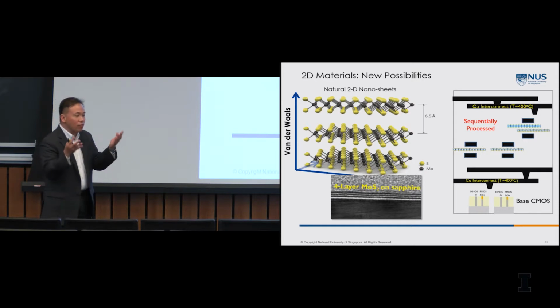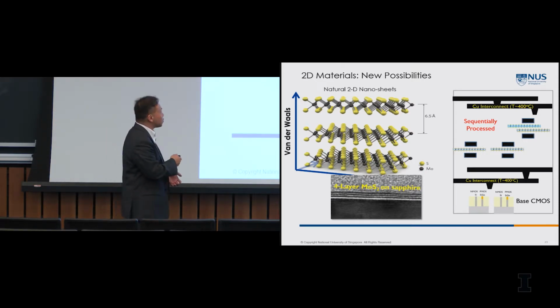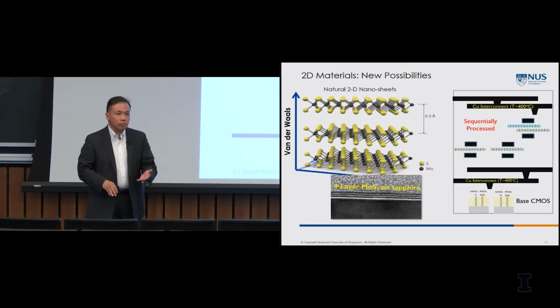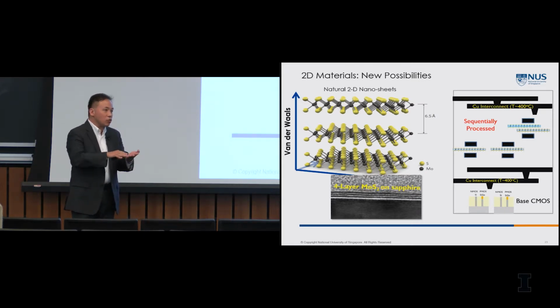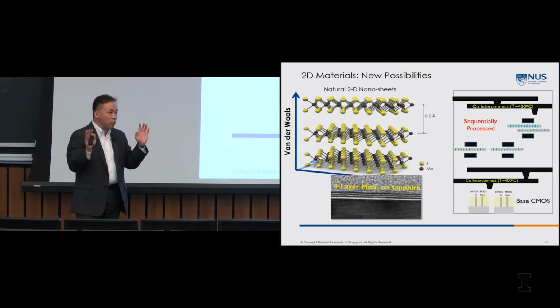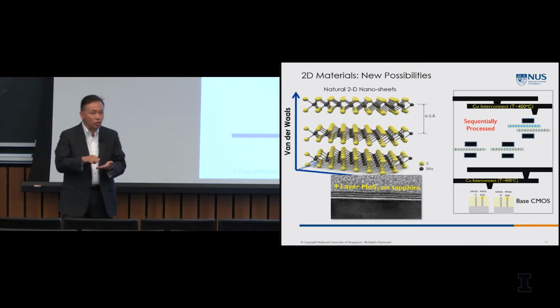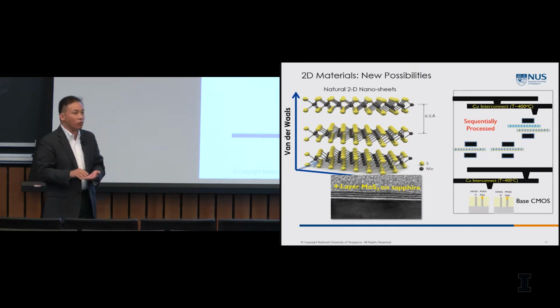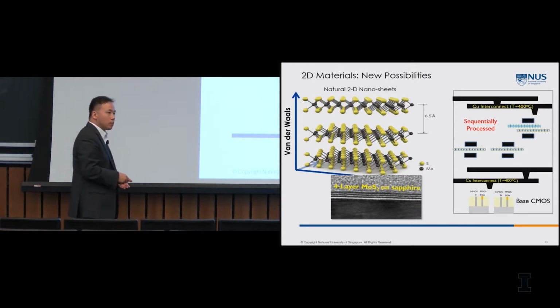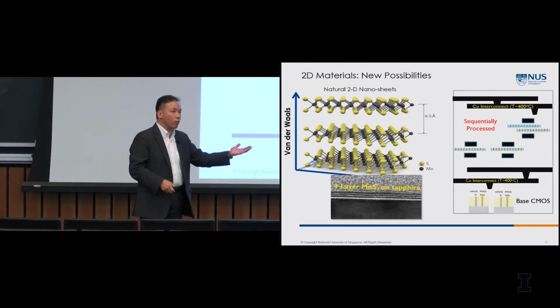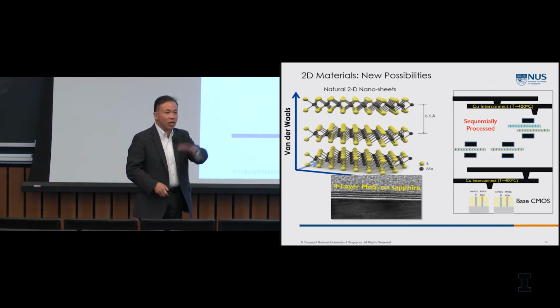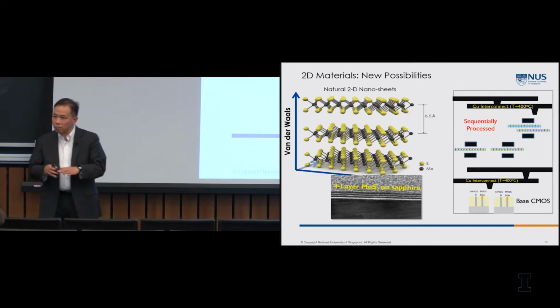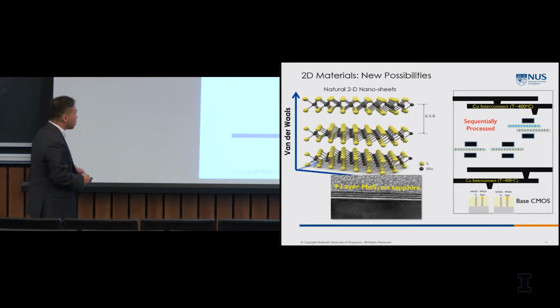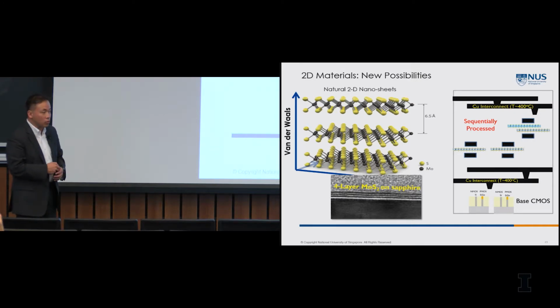If you can do large area, 2D materials are these materials where they are fundamentally cousins of graphene, for instance. They're two-dimensional materials with little defects in principle. They do not need any intrinsic high anneal for doping, activation of dopants. It can happen in stacks. You can put them in the back end without any problem. Same thing: you grow it somewhere, large area, transfer them onto silicon, and then process at low temperature. Right? So this is one very important application for 2D materials, and that's why it's interesting to look at that.